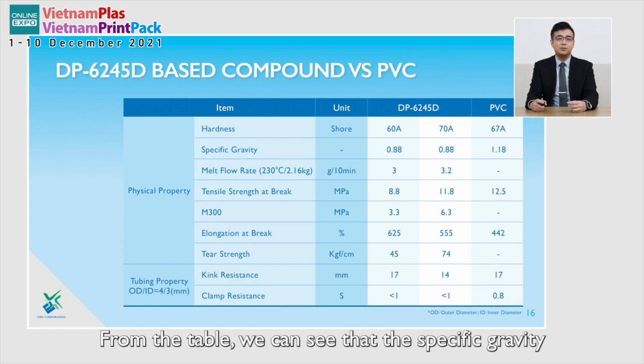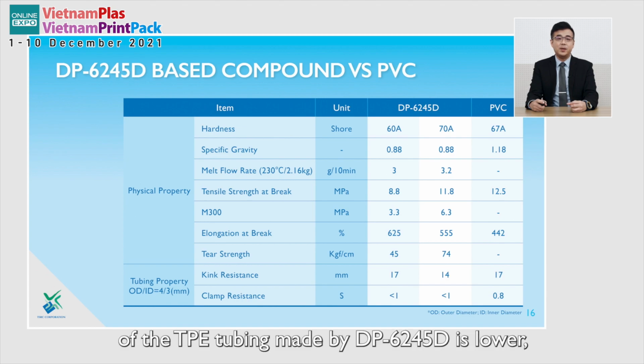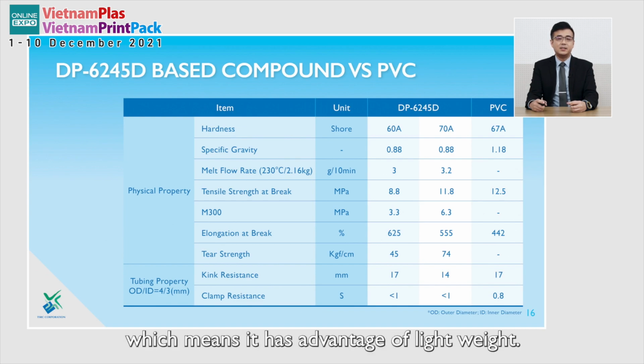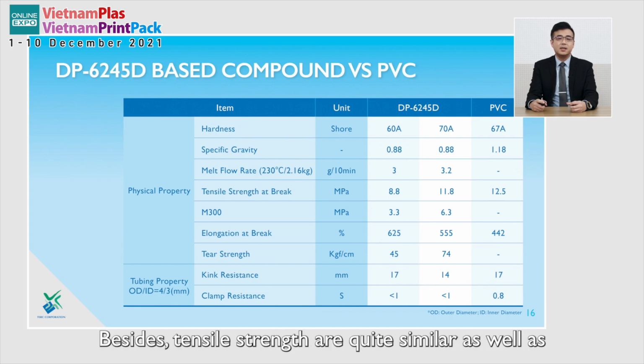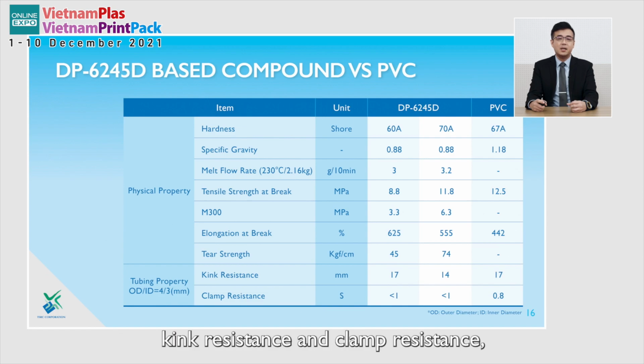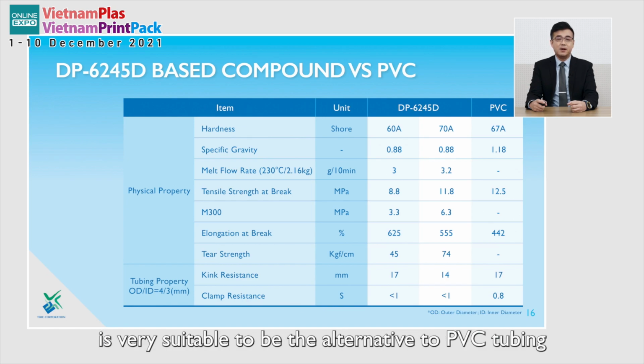From the table, we can see that the specific gravity of the TPE tubing made by DP-6245D is lower, which means it has the advantage of being lightweight. Besides, tensile strengths are quite similar, as well as kink resistance and clamp resistance. So the tubing made by SEBS DP-6245D is very suitable to be an alternative to PVC tubing.